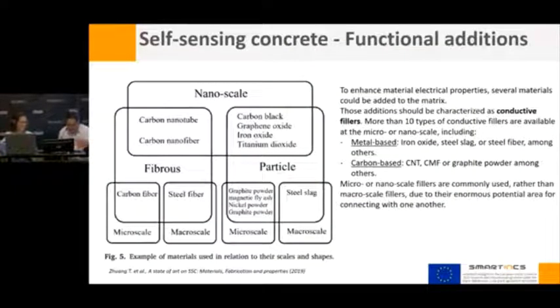The main objective of this project is to implement the property of self-diagnosis as self-sensitive concrete through the incorporation of different types and sizes of carbon-based additions that incorporate the piezo-resistivity property, providing it with electrical properties independent of the humidity of the material. In this first step, the addition provides the material, at multi-scale and multi-phase level, with the possibility of measuring a sensitive signal. This signal relates electrical and mechanical parameters through piezo-resistivity due to the effect of carbon-based additions.